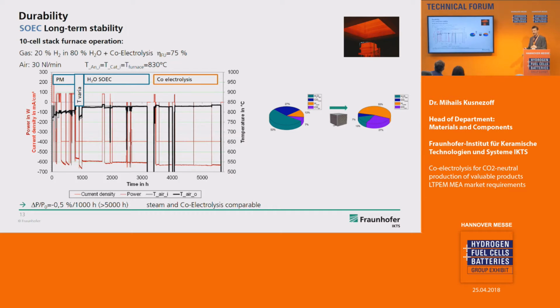We can also answer the question about durability, because this is a main problem. Such units should run for many tens of thousands of hours. And the stack is a main component, the most important and expensive component. And we should always enhance the durability. Now we are in the range of 0.5% per 1,000 hours degradation. We should reduce it below 0.3 to get to a reliable commercial level.